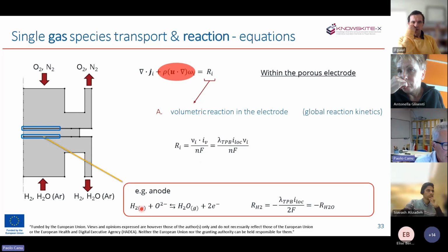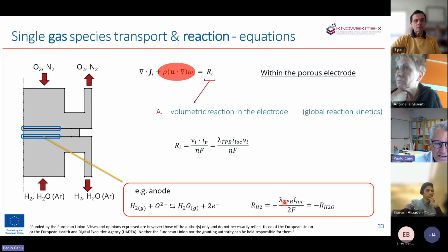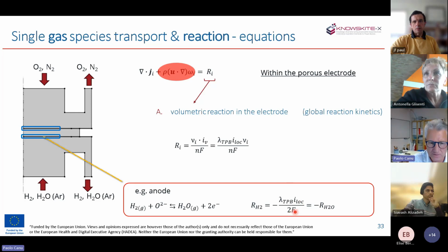So for example, on the anode side, the hydrogen, by means of this global reaction, is assumed to react with oxygen ions coming from the cathode side. The rate of production of hydrogen is indeed negative, so it will be a rate of consumption that is proportional to the length of the triple phase boundary and the intensity of the current at the triple phase boundary, corrected by the Faraday constant. And the rate of production of hydrogen is the opposite of the rate of production of steam. Because the first one is negative, the negative of the negative becomes a positive, so steam is produced at the anode.